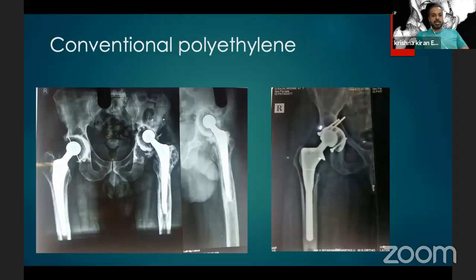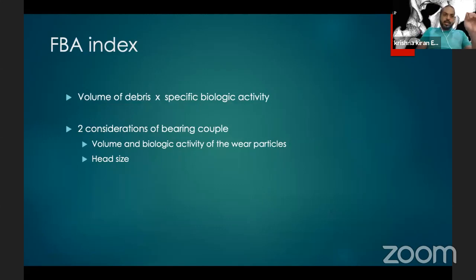And this is how an osteolytic lesion looks, where there is global osteolysis following a cemented cup failure. And here is an uncemented cup failure because of progressive polyethylene wear. You can see the eccentric positioning of the femoral head inside the cup. That is a way to determine the presence of polyethylene wear. And you can see behind the cup, there are large osteolytic segments because of the wear particle induced bone resorption.